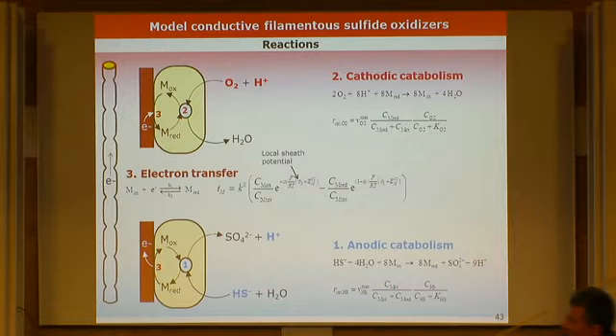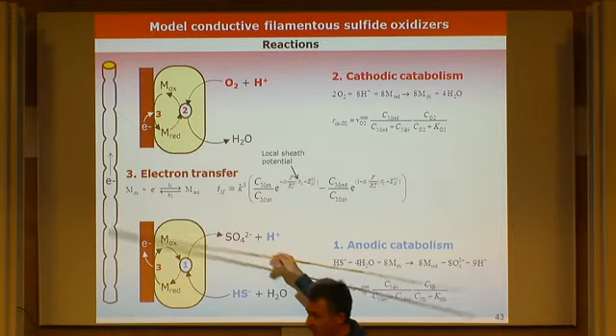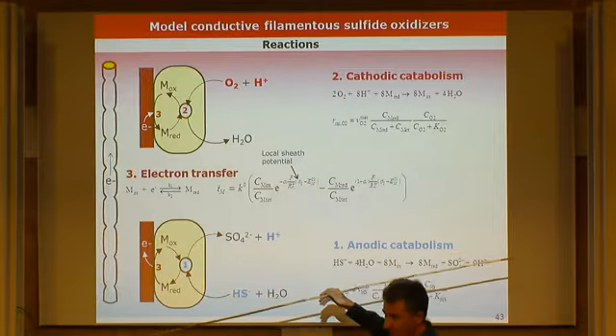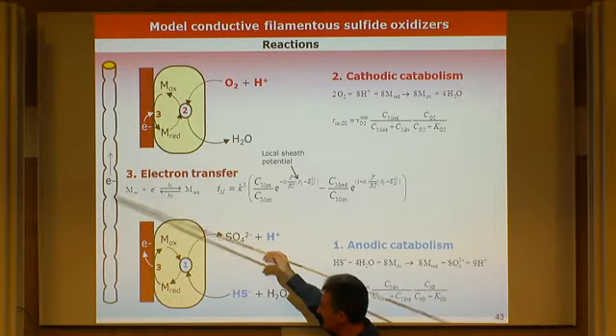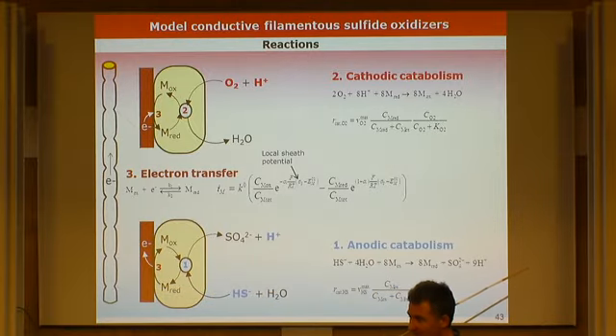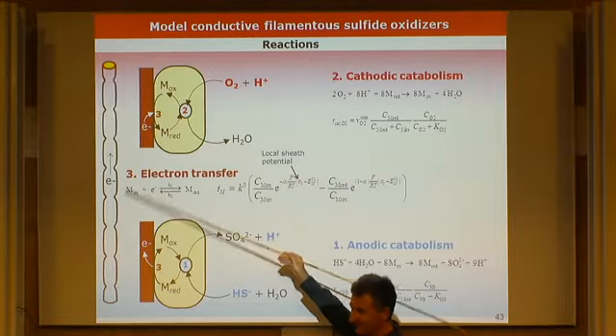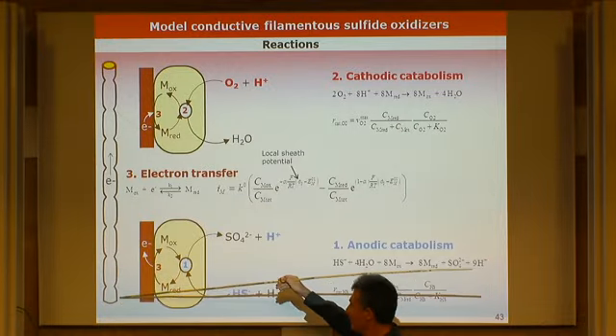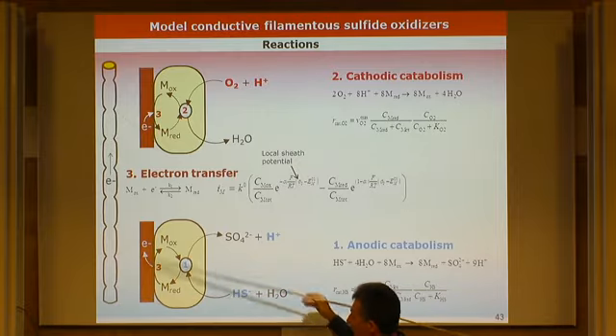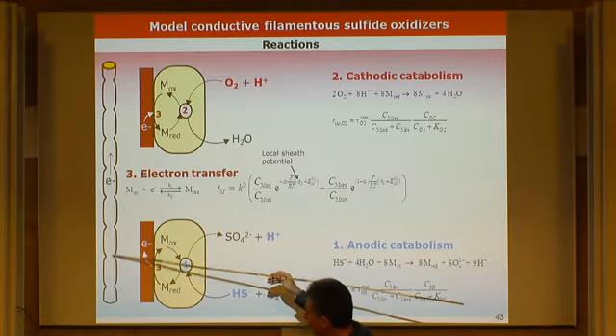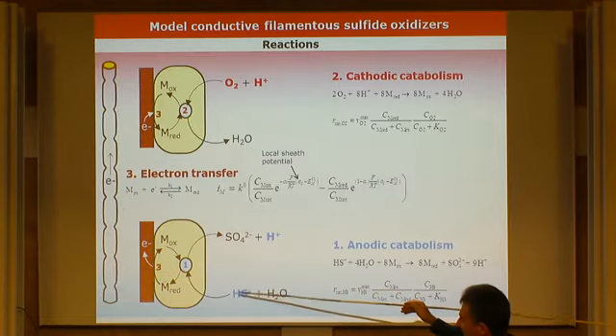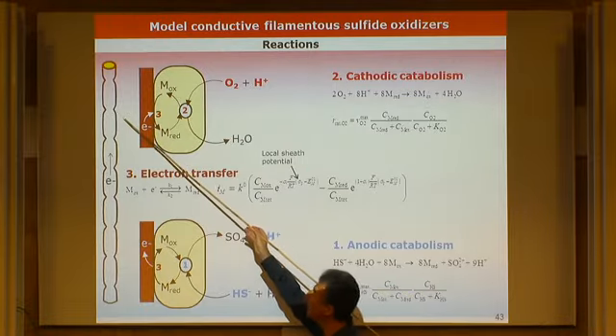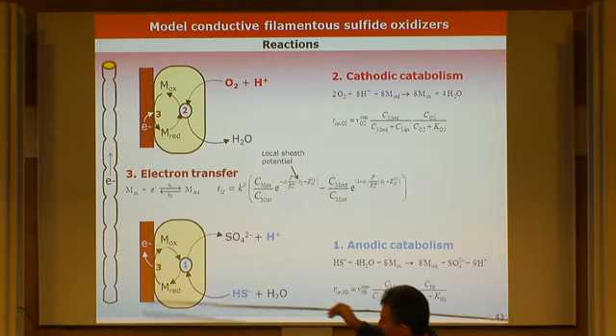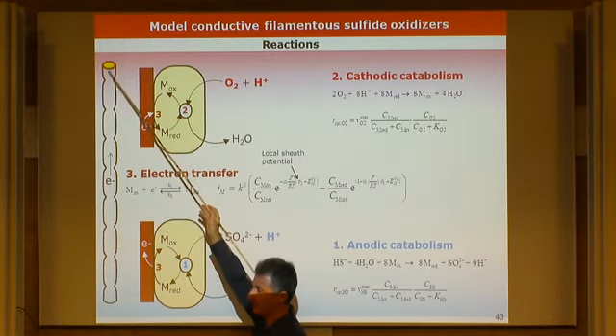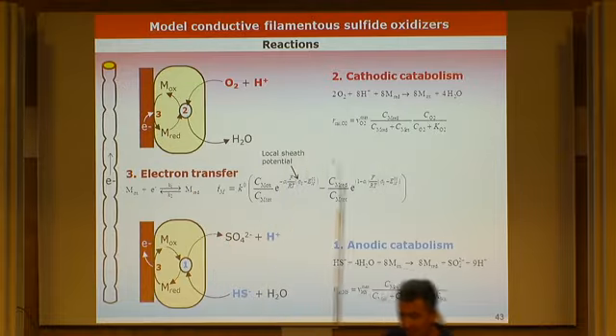And you can imagine there is now a potential difference between these two areas. Otherwise, it wouldn't work. And this potential difference arises from conductivity. So if conductivity is infinite, then it's the same potential everywhere, like in a metal. But this is, I think, the whole trick here. The conductivity is not infinite, so you have a potential favorable here for sulfide oxidation and here for oxygen reduction. And all the electrons are contained within the filament. You insulate the ends.